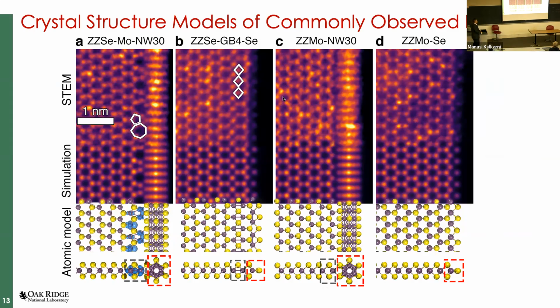So oftentimes what we like to do in STEM images is we have an idea of what the crystal structure is. We can create a structural model. We can run it through some code to do multi-slice image simulations to get an answer of what the intensities look like, and we can see if it's a perfect match. And why this is so important is once we have this atomic structure model, we can start to do some really fun stuff and start to tease out some of the properties of these edges that we just engineered in a 2D material semiconductor.